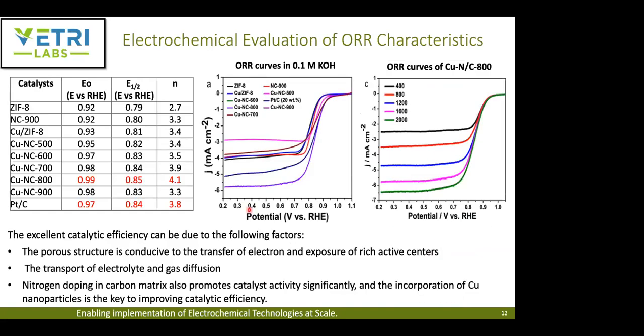So moving on to the electrochemical evaluation. They did all this electrochemical evaluation in alkaline medium. As you can see, they did the linear sweep voltammetry, scanning from about 1.1 volt to about 0.2 volt with respect to RHE. But in their actual experiment, they used a standard calomel electrode, and they did the conversion into RHE. And as we can see, the table summarizes the onset potential, the half-wave potential, and the electron transfer number. I mentioned earlier in the presentation that for an ideal ORR catalyst, you want this electron transfer number to be close to 4. So they calculated this electron transfer number using the Koutecky-Levich plot to identify the overall number of electrons involved in this reaction. And so we can compare.